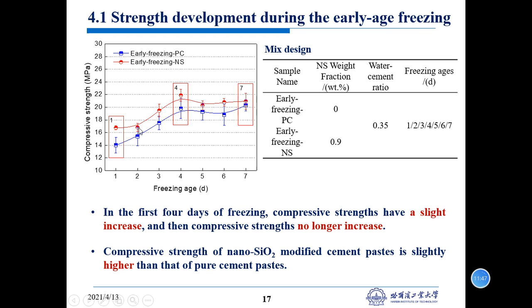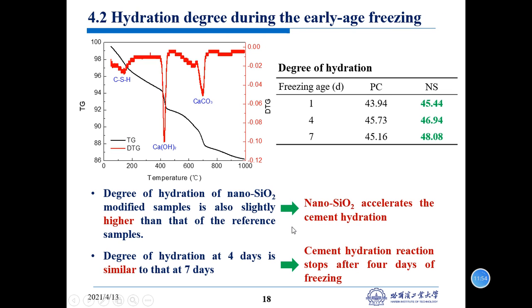Based on this result, we chose 1 day, 4 days, and 7 days to carry out the TG test. This table is the degree of hydration, and we can see the degree of hydration of the nano-silica modified sample is also slightly higher than that of the reference sample. We also see the degree of hydration at 4 days is similar to that at 7 days. So we can see the nano-silica accelerates the cement hydration, and we also see the cement hydration reaction stops after 4 days of freezing.